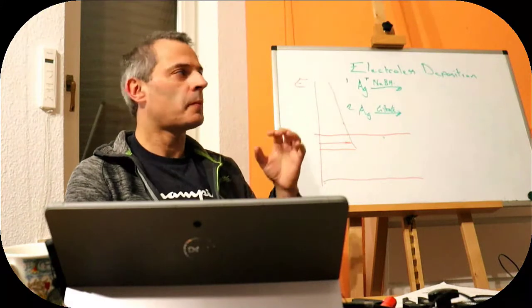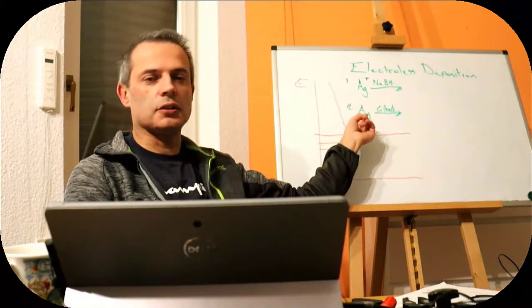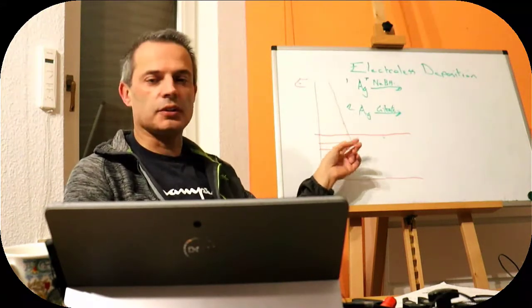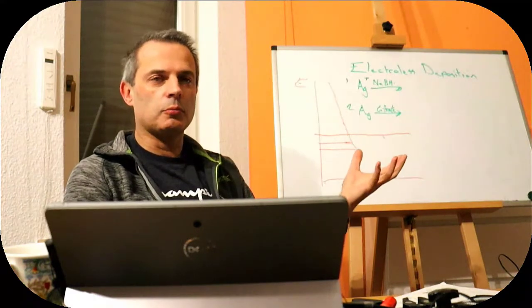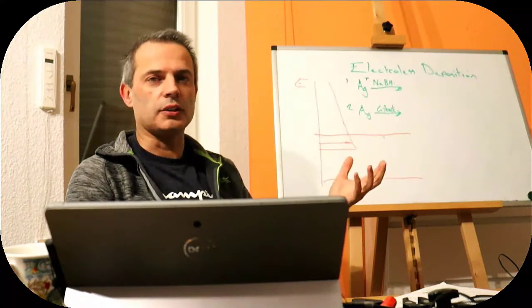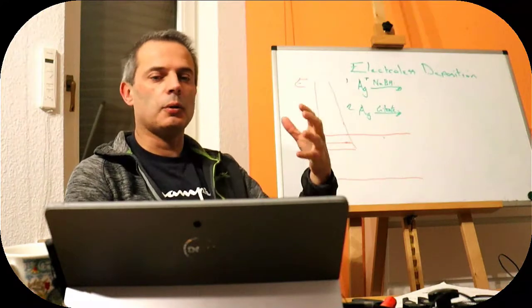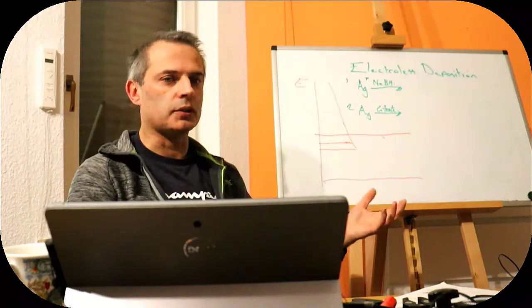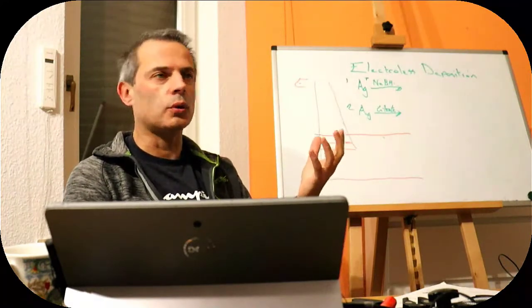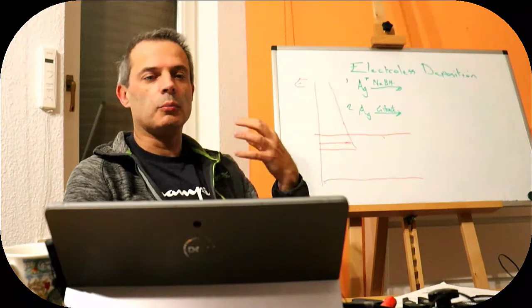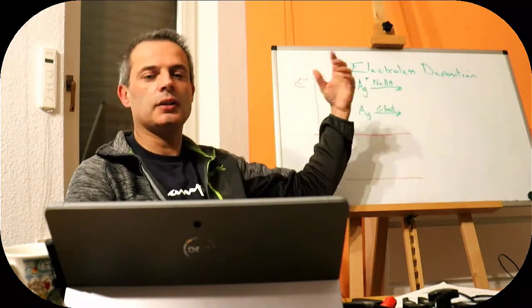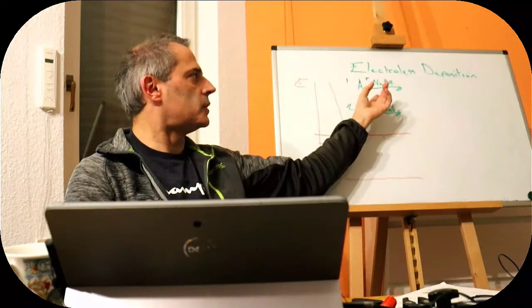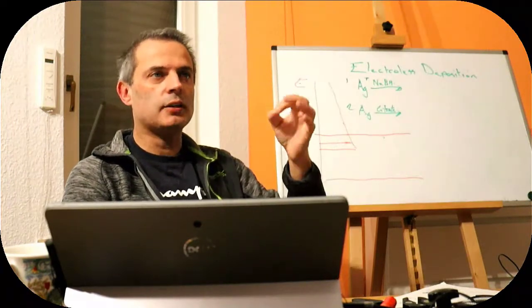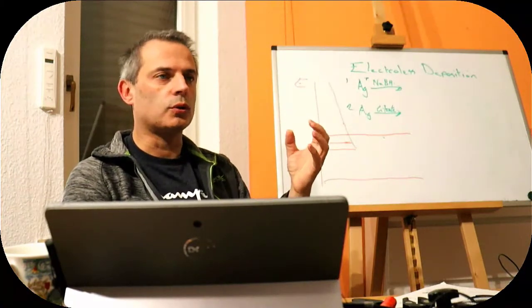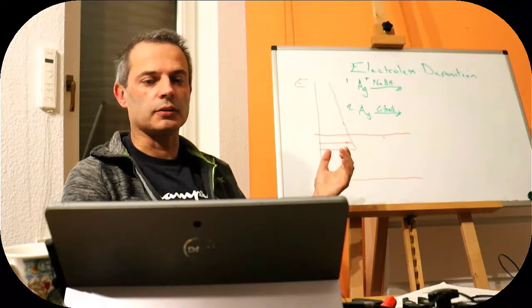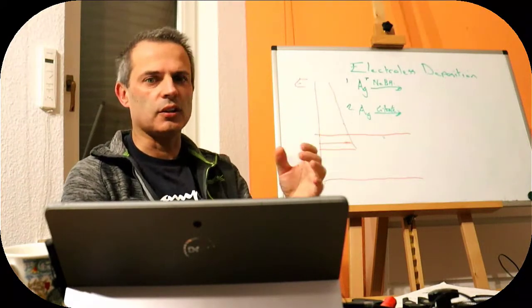standard size. Otherwise, if we use just citrate, we pass this very slowly and we generate some particles, and then we carry on generating new nuclei, and we also make big particles and small particles, and we have very little control over how many nuclei form because we're not passing very quickly, which means that any random differences in the solution will cause us to get more or less particles. I said particle a lot, I know.